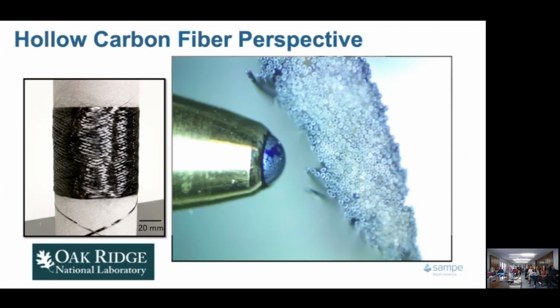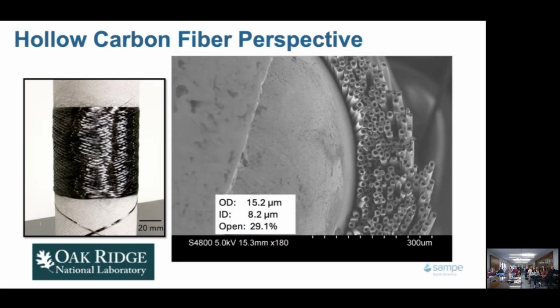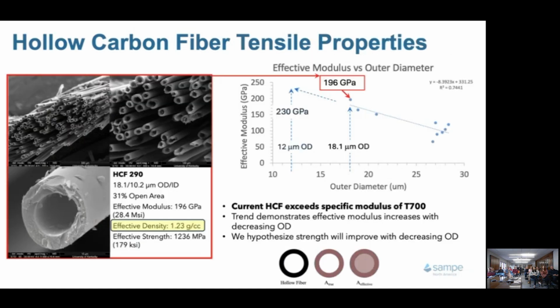We have, with our partners at Oak Ridge, been able to take continuous tows of the hollow filaments and convert those into carbon fiber continuously; this is an experimental result of that. If we look in the SEM, this is the same ballpoint pen with these hollow carbon fibers, down to about 15 micron on the diameter. We still need to get that smaller.